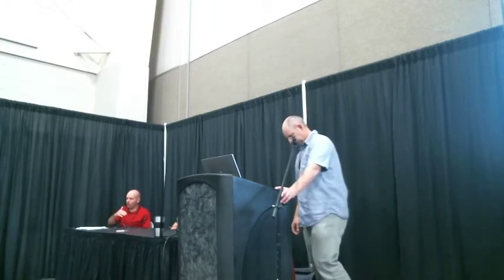So real quick, Charlie, he talked about putting that on there to keep the dust down. I hope you can hear me. That's one issue with cement treated base in general, right? Is you want to put the cement down on top and then mix it in. And in a lot of environments, that dust is a real problem. Fortunately, we didn't have that problem here, right? We're up in the canyon in the middle of nowhere where I don't have a resident on the side of the road complaining about dust. But if you're going to select a cement treated base, you really have to think, is dust going to be a problem?